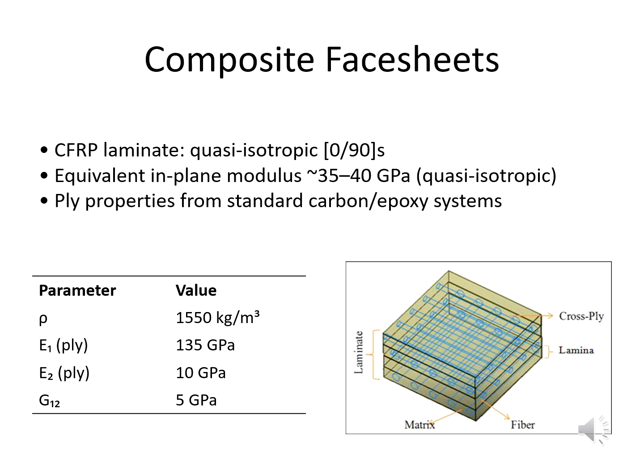The composite skins are modeled using ANSYS ACP Pre/Post with a quasi-isotropic layup of 0 and 90 degrees. This configuration provides balanced stiffness, which is ideal for components that experience multidirectional loading.